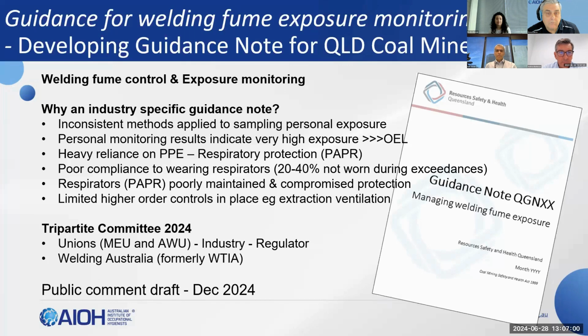We went out and did a couple of years of compliance type structured inspection surveys across about 50% of the coal mines in Queensland. And from that inspection regime, we discovered also that there was a heavier reliance on PAPR respirators, and there was poor compliance to wearing respirators. Out of the data that we collected back in 2021, we found that of the exceedances reported, between 20 to 40% of those exceedances, the wearer reported they weren't wearing any form of respiratory protection. So while we are relying on respiratory protection, we're not using it a lot, and it's not been particularly effective.